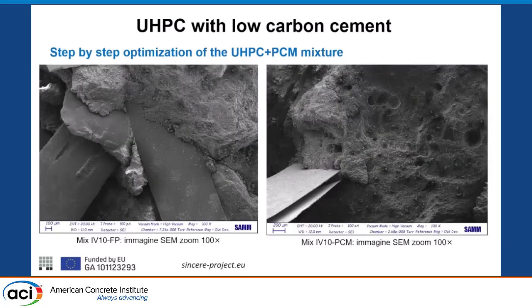We used in this case not steel fibers, but commercial ones, these amorphous alloy fibers. The good thing is that their specific gravity is more or less similar to the one of steel. So when you perform a mix design and adjust the fresh state performance, the same criteria that you use for steel fibers are good as well for these amorphous alloy fibers. They come in the form of a very thin lamella, and they are not like needles. So this makes them interesting.